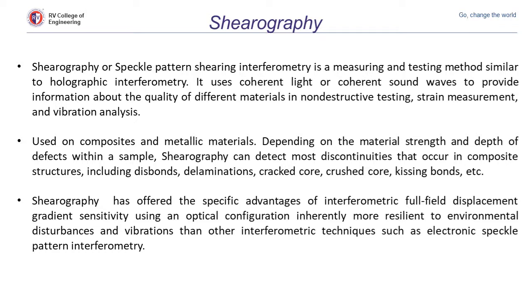The next method is shearography, also known as speckle pattern shearing interferometry. It is actually very similar to holographic method. It uses coherent light or coherent sound waves to provide information for different materials, and it measures the strain to determine the deformation. It can be done on composite and metallic plates, and depending on the material strength and depth of the defect, shearography can detect most discontinuities that occur in a composite structure such as disbond, crack cores, etc. Shearography offers a specific advantage of interferometry providing displacement gradient sensitivity using an optical configuration that is inherently resilient to environmental disturbance or vibration, giving very accurate results.